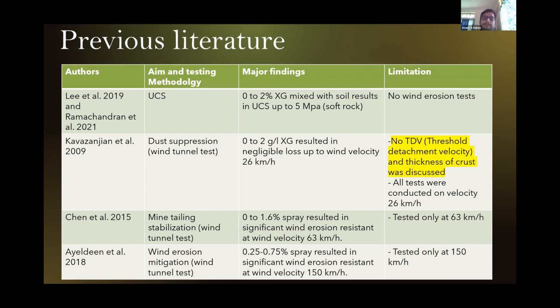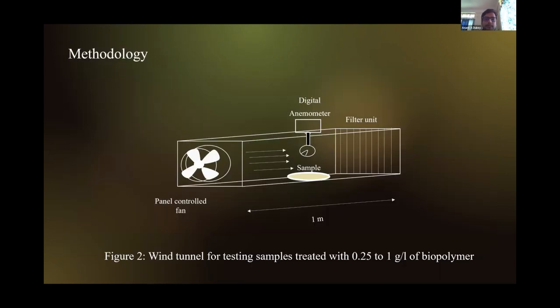So TDV, that means threshold detachment velocity, is the velocity at which a particle starts to move. And since it is a very important parameter, according to that the dosage of biopolymer can be decided. So seeing all these limitations, we conducted our tests in a small wind tunnel. It is a manufactured wind tunnel in which the soil samples are kept and the motorized fan speed can be controlled. There is a digital anemometer placed just above the soil sample to measure the actual wind velocity.